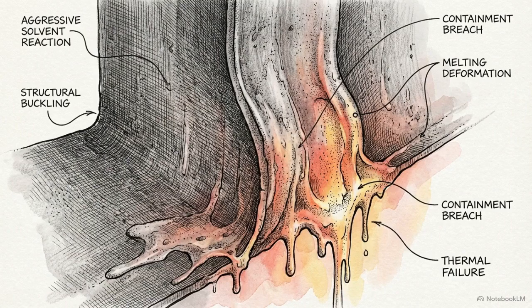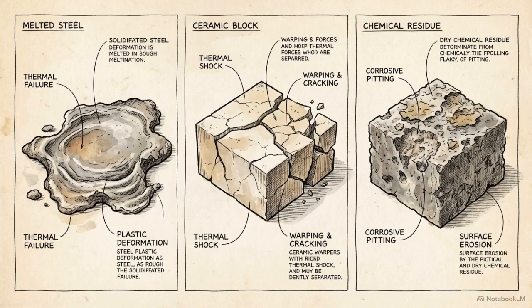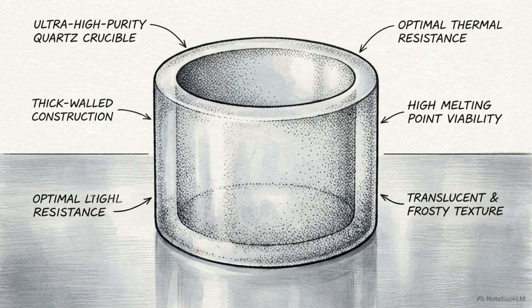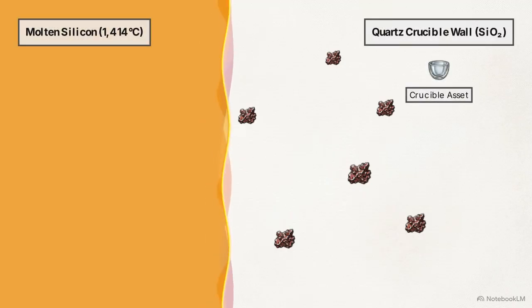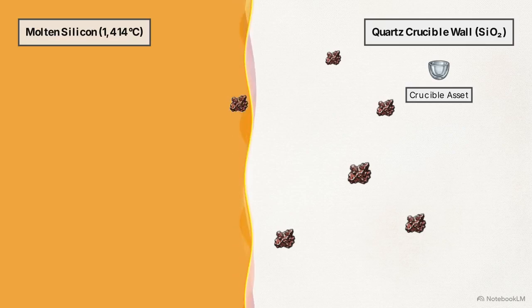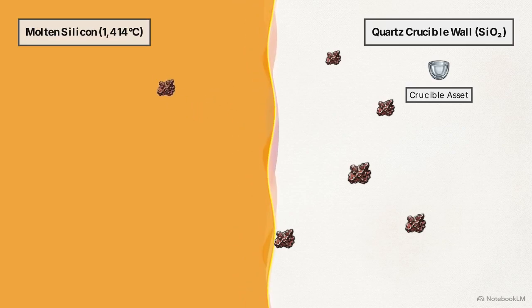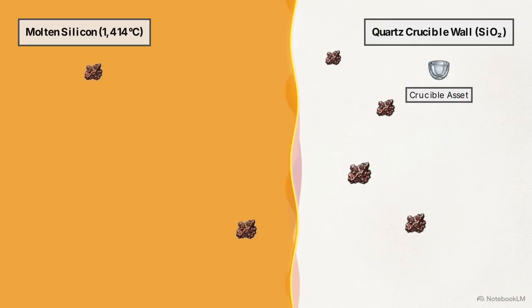This creates a severe containment paradox. At 1414 degrees, liquid silicon is a highly aggressive solvent. Almost every known material on Earth will either melt, structurally deform, or chemically react with the liquid, ruining the batch. The only physically viable solution is a specialized containment vessel, a crucible, made entirely of ultra-high purity fused quartz glass. Because the highly reactive liquid silicon slowly physically erodes those quartz walls over time, the crucible itself becomes the primary source of potential atomic contamination.